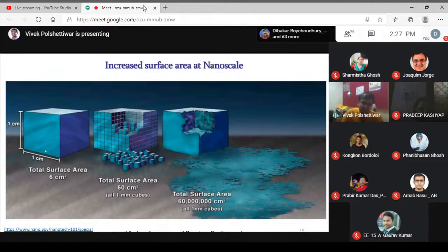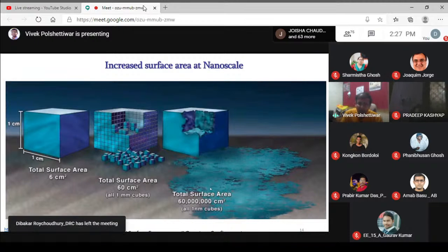If I take a 1 centimeter by 1 centimeter cube, the surface area will be around 6 square centimeters. If I break that 1 centimeter cube into 1 millimeter cubes, then the total surface area will be 60 square centimeters. There is an increase, but not much, 6 to 60. However, if you now reduce the cube size from 1 mm to 1 nanometer, you see 60,000,000 square centimeters. It's a huge surface area. So that's the difference. When you go from bulk to nanoscale, there is an increase in the surface area.